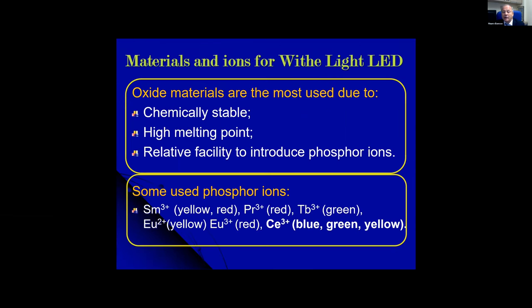Well, why oxide glass? This is an important point, because it is chemically stable, it has a high melting temperature, and it is relatively facile to introduce phosphor ions. And also, it can be used in hostile environments. So oxide glass has this kind of advantages. And of course, I listed some of the ions that should be used for doping, but of course there are more.